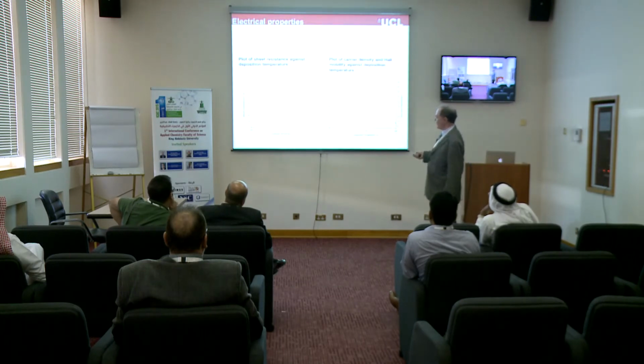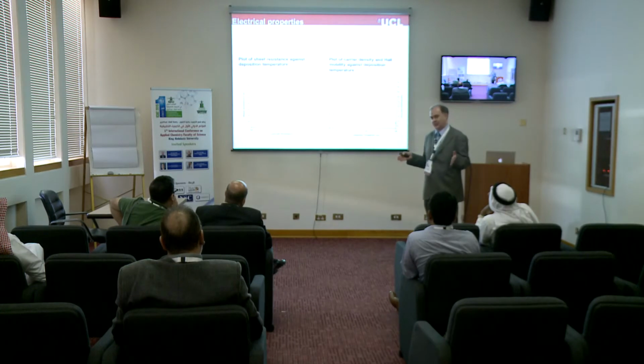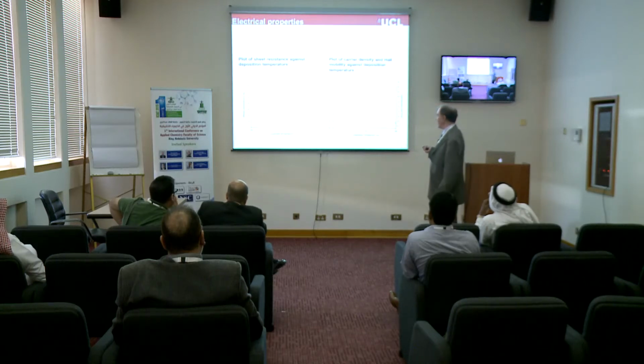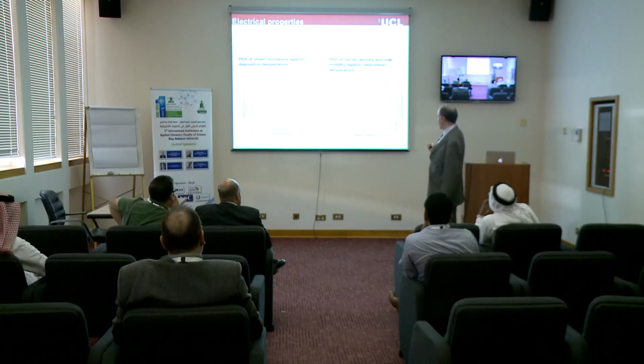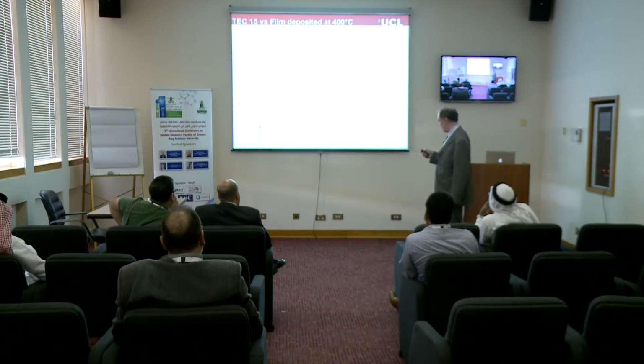So when we do that, and we look at the sheet resistance, we get sheet resistance values of around 2 ohms per square. To give you an idea, the best commercial products are around 10 ohms per square. So we can make with this product, or this methodology, a better material than is available commercially. So at the moment, we're looking to scale this up with industry. In particular, we get quite high mobilities for our films. So the sheet resistance is made up of mobility and charge carrier concentrations, and ideally you want a high mobility, and that's what we get from these particular films.